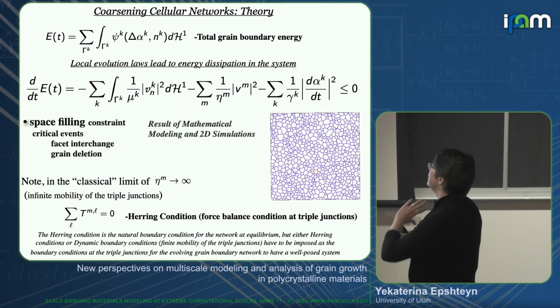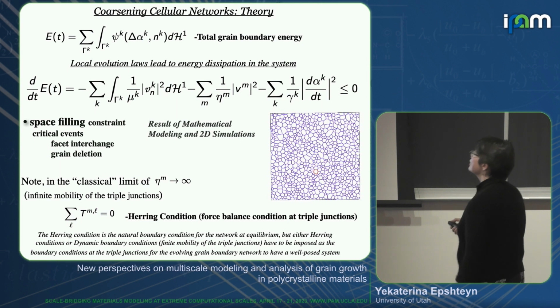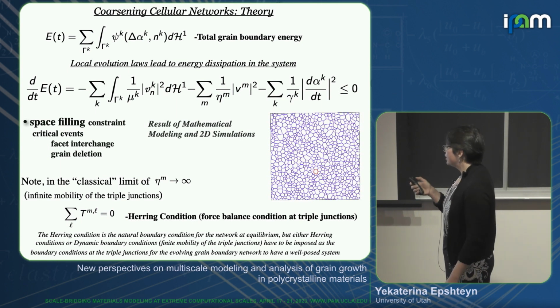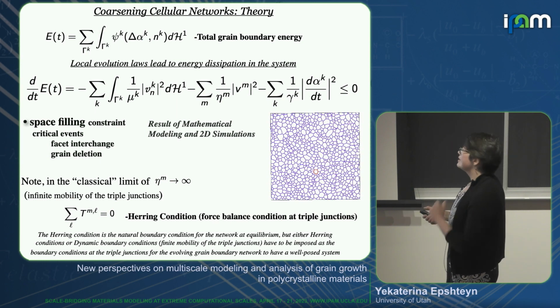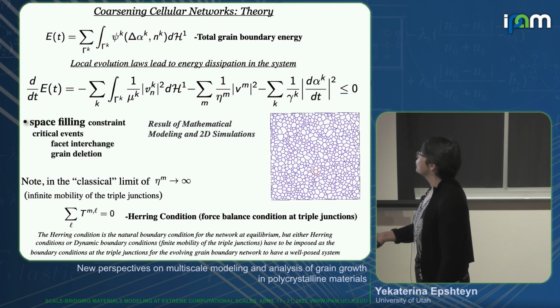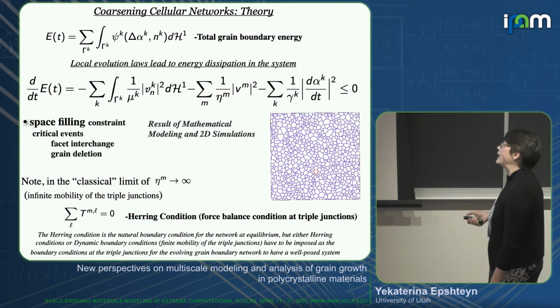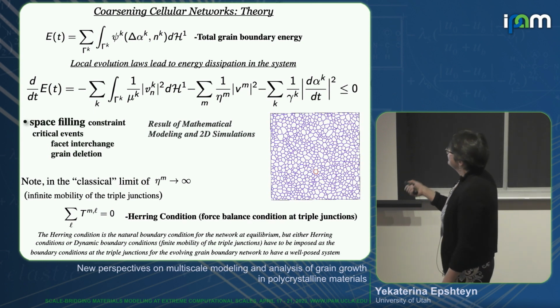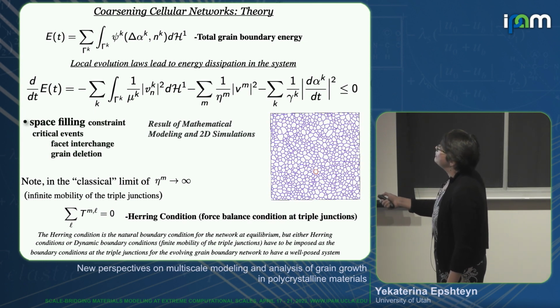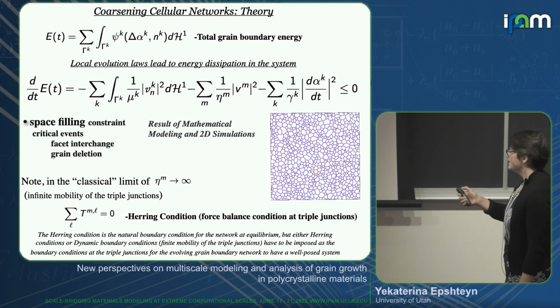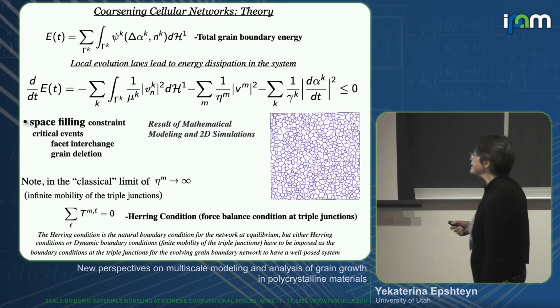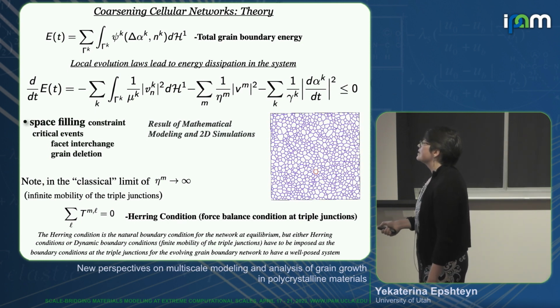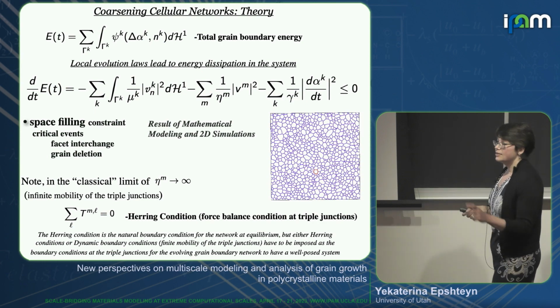In the classical, at least in most mathematical literature, usually you do not have this term. So the classical assumption, you assume a force balance condition, so Herring conditions at the triple junctions. So what you do, you set mobility of triple junctions to infinity, so this term disappears. And this is actually a natural boundary